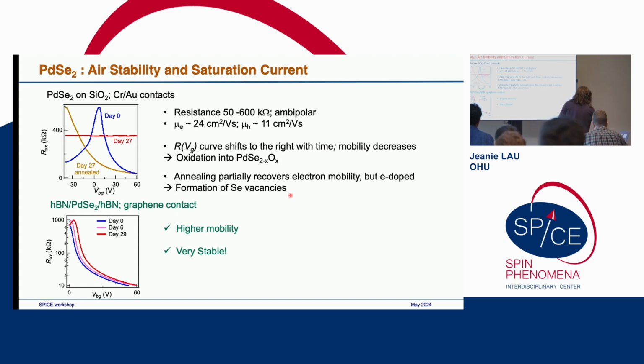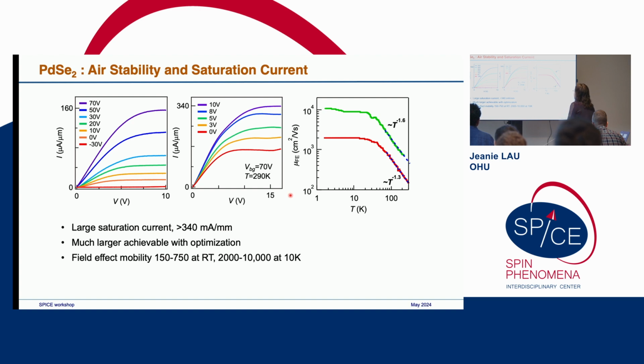Okay, so we can do some characterization. This is done at, I think, room temperature. For example, we can have very large saturation current, greater than 340 milliamp per millimeter. And we believe we can achieve a much larger saturation current with some optimization. The field effect mobility: these are two devices. One is, I think, 3 layers. The other is 5 layers. So the 5 layers have higher mobility up here.